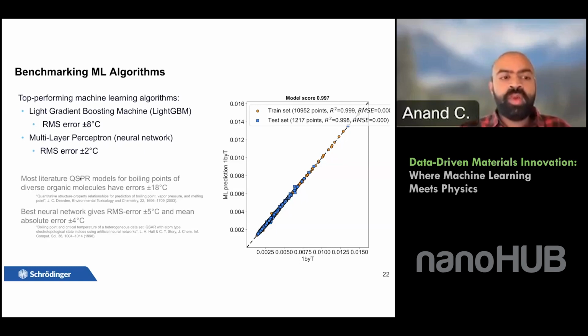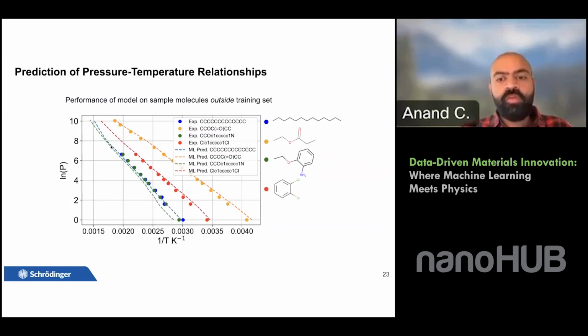And we looked at how well this machine learning model extrapolates. For example, these four molecules are extremely diverse, and they were not part of the training set of this particular model. You can see here that the dots represent the experimental measurements for the volatility of these four different molecules, and the dashed line represents the machine learning prediction. You can see the machine learning model is able to accurately predict the volatility of these compounds, and it's also able to extrapolate to higher temperatures as well. So we had to be very careful about choosing the right model. For example, if you had chosen a tree-based model, this extrapolation to higher temperatures may not have been possible because of the architecture of a tree-based model.